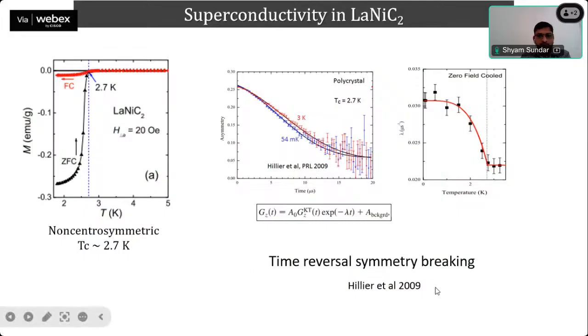And why it was interesting is that in 2009, they saw something called time reversal symmetry breaking. What exactly did they see? They did a zero-field muSR experiment. You can see this is measured at 3 Kelvin and at 54 millikelvin, and there is a clear difference. When they did this at several temperatures and analyzed the data with this equation, they got this relaxation rate as a function of temperature. They see the relaxation rate starts increasing exactly at TC and shows an order-parameter-like behavior. So this tells you there is a spontaneous magnetic field appearing at TC, which is a signature of time reversal symmetry breaking. So this tells you the superconductor is not conventional.